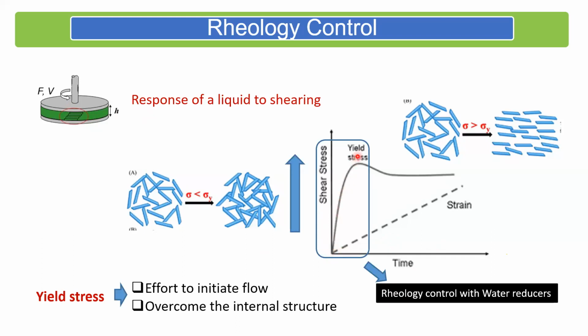Initially, the shear stress increases, reaches a maximum, and then it basically levels off at some constant value as I keep on increasing the applied shear strain on the liquid. So this kind of interesting behavior, where initially the resistance increases and then levels off, required some understanding. And now we understand that this peak here is identified with what is known as yield stress. This is called the yield stress of the liquid. It's not of the solid. And under increasing strain, eventually I attain a steady state. This is where the liquid starts flowing in a steady state. What is happening up to this point, in this box that I've shown here, is called the transient state.